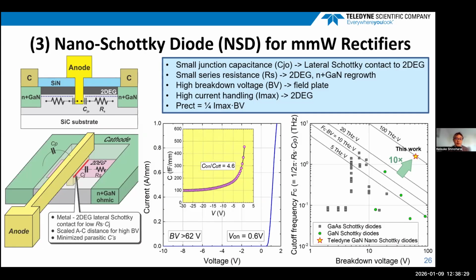In the middle, I show the CV characteristics of such a device and also the IV characteristics. The device shows a very low turn-on voltage of 0.6 volt with very high current density exceeding 1 amp per millimeter. We also optimized the electric field distribution, enabling a breakdown voltage of over 62 volts. And the Con/Coff ratio is 4.6, as shown here. On the right, I plotted the cutoff frequency, which is 1 over 2 pi Rs Cj0, as a function of breakdown voltage in comparison to conventional gallium arsenide Schottky diodes, as well as vertical gallium nitride Schottky diodes. So this device shows a 10x improvement.